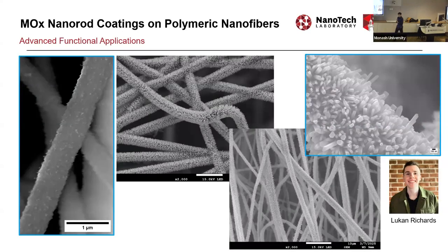Lastly, we use flame pyrolysis as a seeding process to create seeds on top of, again, literally everything. What you see here is a polymeric fiber being exposed to flame pyrolysis for 1 second, and you see all those tiny zinc oxide seeds. So this is my undergrad student, so the quality of this image is not very high. Then he put them in a solvent, hydrothermal, and he grew all these nanorods from the fiber.